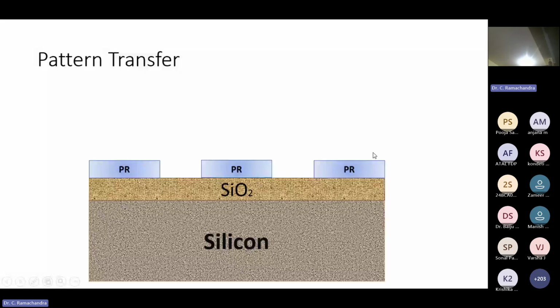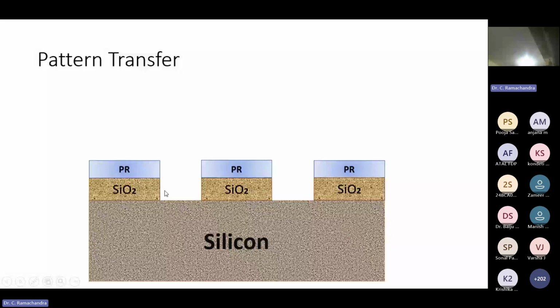Now using this one, I am removing silicon dioxide using chemicals, meaning certain plasma etching. Wherever photoresist is there, it is blocking the silicon dioxide. Therefore, wherever photoresist is not there, it is allowing silicon dioxide to be etched. So from this structure, I am etching silicon dioxide so that wherever photoresist is not there, it will etch in that direction. So when I do that, I get a structure. See, silicon dioxide is etched wherever photoresist is not there. So I get a structure like this. Now, the purpose of photoresist is done. It is over. So I'm going to remove the photoresist. When I remove the photoresist, I get this structure.